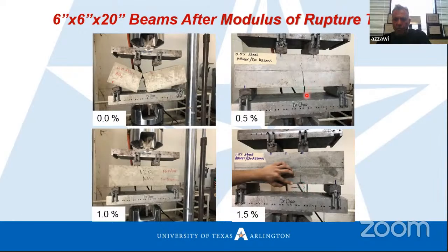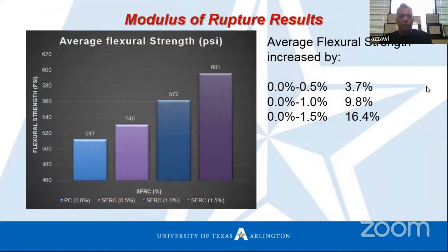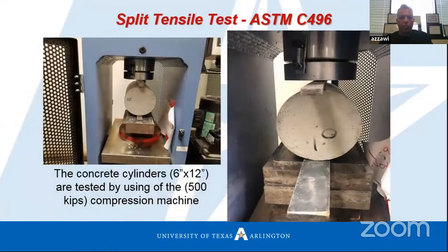With 0.5%, we have cracks. It's noticeable. With 1% and 1.5%, we have a crack and it failed, but the behavior is still ductile. These are the modulus of rupture results. And as we see, there's a noticeable increase in the modulus of rupture for concrete with fibers.